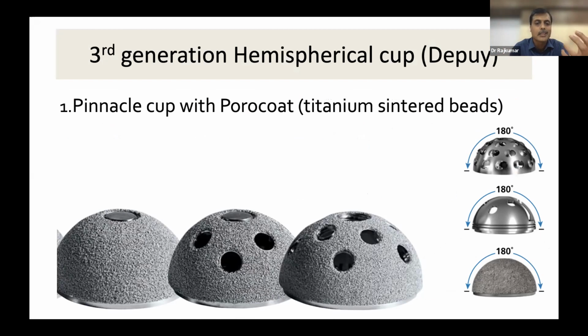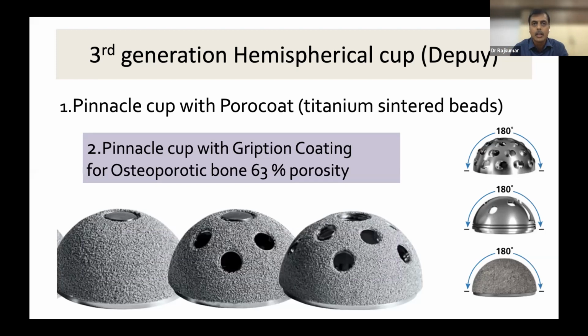For example, the 3rd generation hemispherical cups, I've taken as an example from the DePuy company. If you see the Pinnacle cup with the Porocoat, that is the basic coating. What is that Porocoat? It is titanium sintered beads coated over the titanium shell, and this coating enhances bone integration, osteointegration, over that cup and into that. So the porosity is a little less in this one, but whenever you want a more stable, more adequate fixation, then you need to go for a Gription coating over the Pinnacle cup. That is more commonly used in revision and in osteoporosis situations, with 63% porosity.